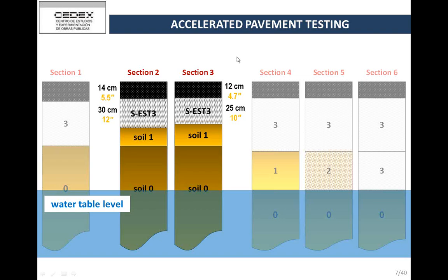Yes. Yeah, we don't even have that movement in section, for example, 4, 5, and 6, where we actually have a regular soil as a capping layer. So in sections 4, 5, and 6, we don't see movement. And a lot of work on this type of failure has been done by Maurice de Beer in South Africa, where essentially he looked at the crumbling, the resistance to compression of the soil cement, not fatigue. So you may not see any major fatigue cracking in the soil cement just because you have this failure and the layers are acting independently. Exactly. In other words, what you're saying is that the structural system is failing, but you see a different performance phenomenon.